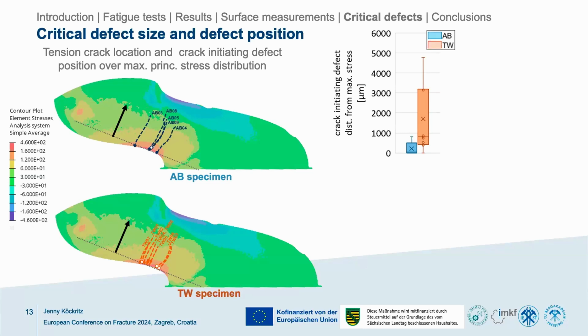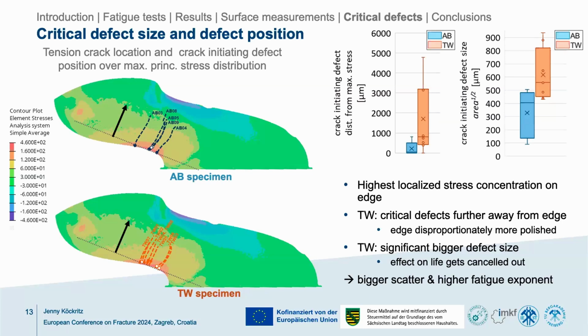Okay, if they're further away, lower acting stress should have a longer life. However, if we look at the defect size, the defects which led to damage in the trovalized specimen were also a lot bigger. So in combination, we have defects which are further away, but have a higher size. And so in combination, the effect on fatigue life kind of gets cancelled out. This explains, however, the bigger scatter for the trovalized specimen, as well as the slightly more inclined SN curve for the trovalized specimen.